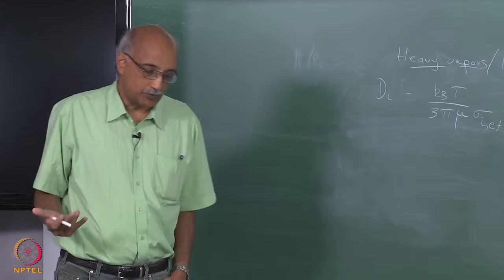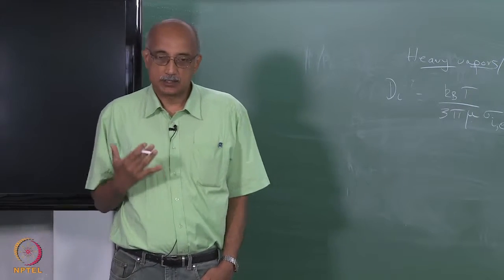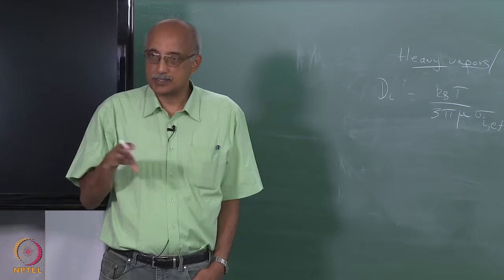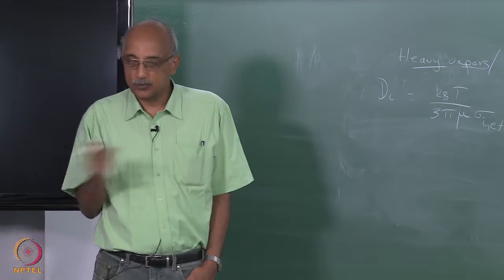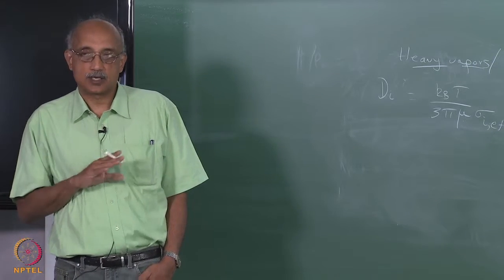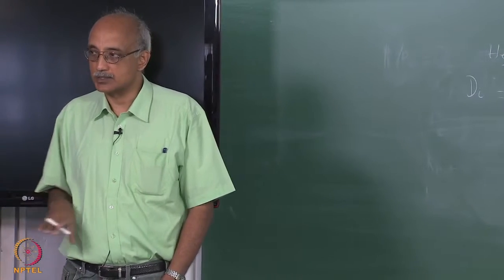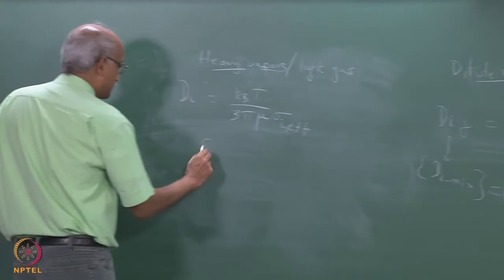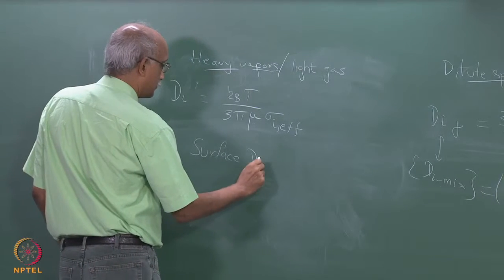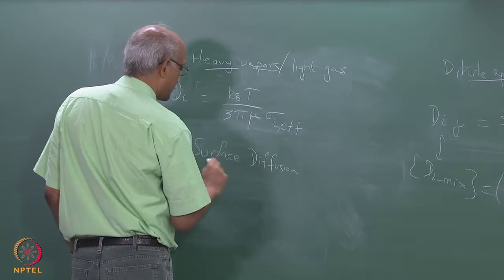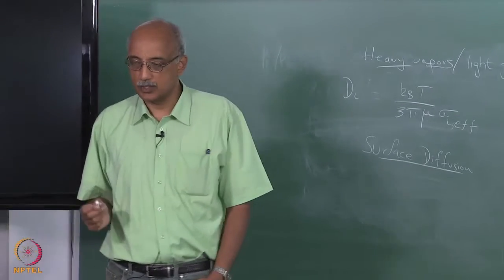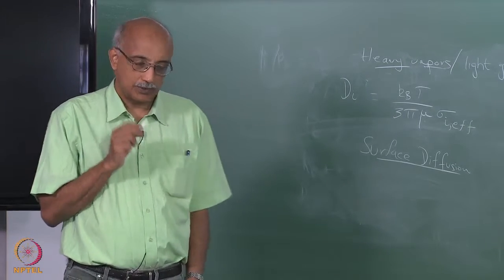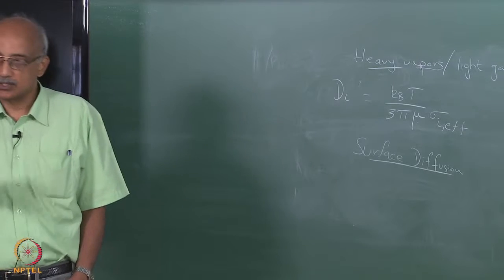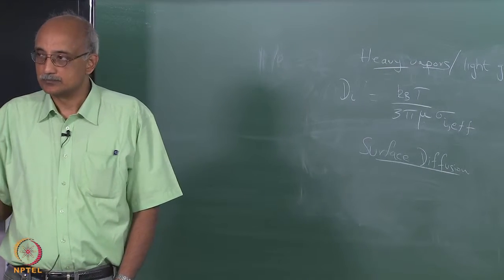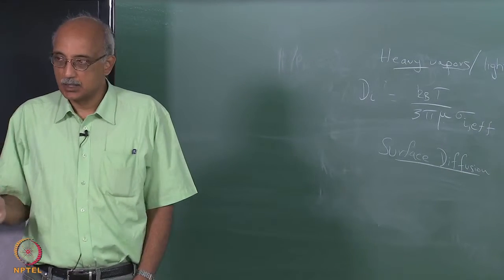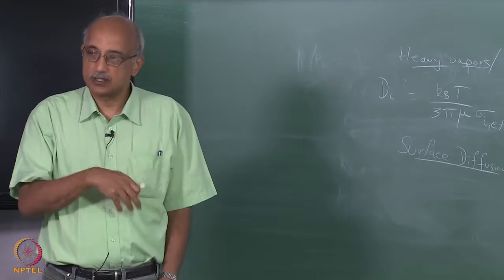So, the other type of diffusion process that can happen is after the molecule has adsorbed on a surface, it has diffusion along the surface. And in fact, that is a very critical process in achieving the final state of the CVD film on the substrate. So, when we talk about surface diffusion, it has very different characteristics when you write the equation. Because in this case, what you are really trying to model is the migration of an adsorbed species from one interstitial site to another. And you are trying to estimate the flux of that, and from the flux you try to estimate the diffusion coefficient.